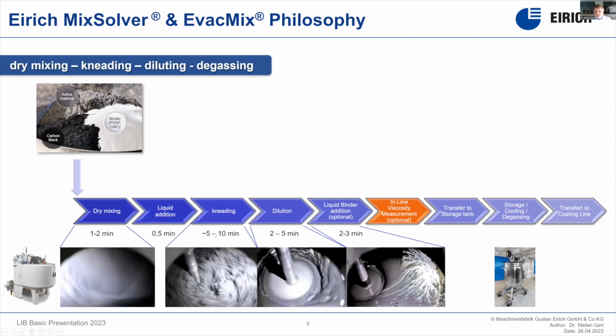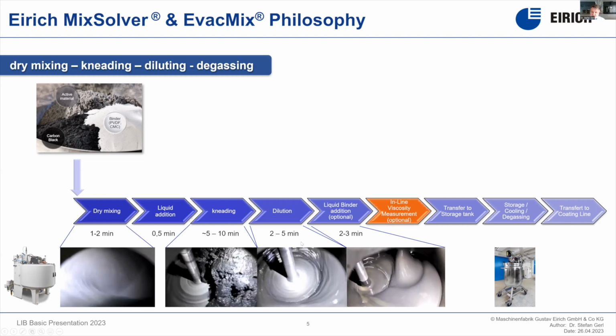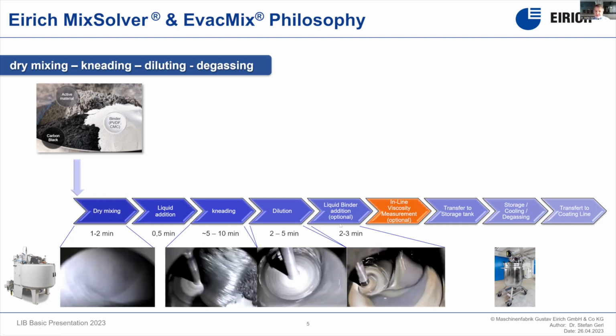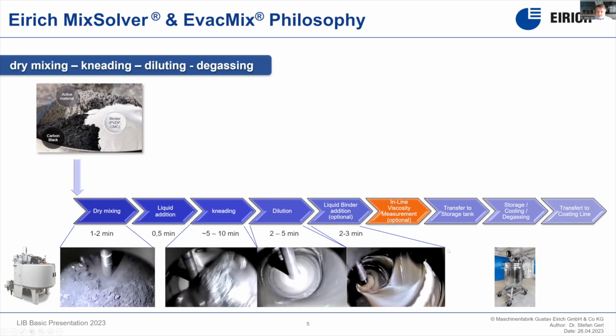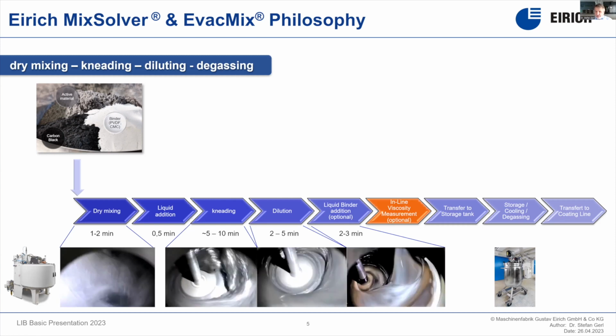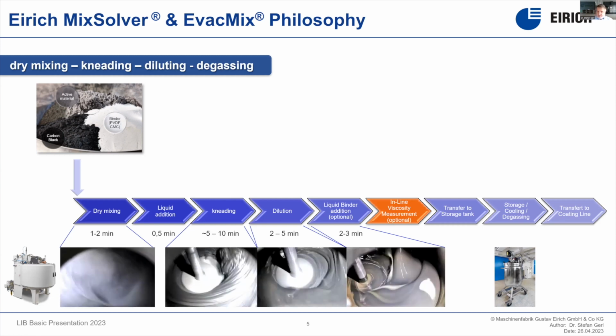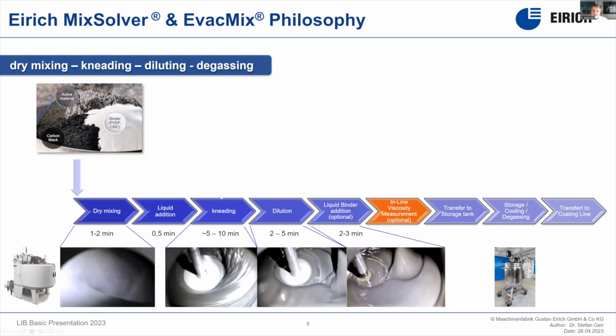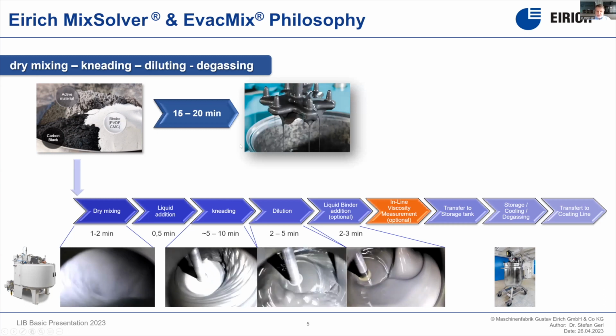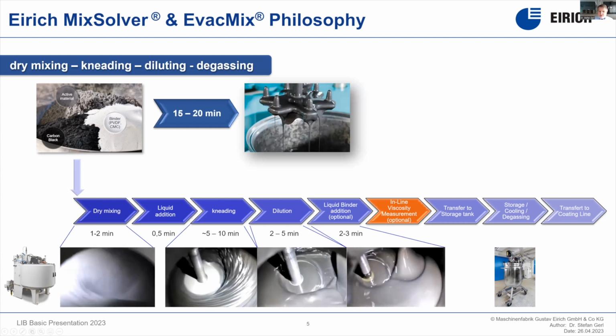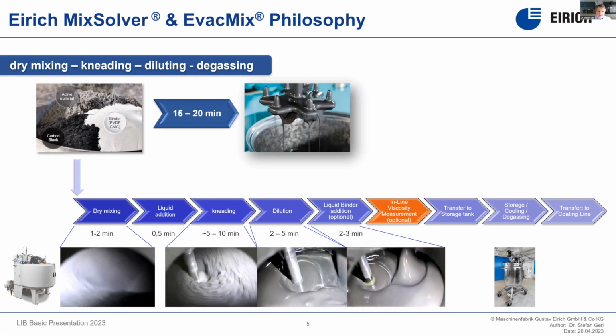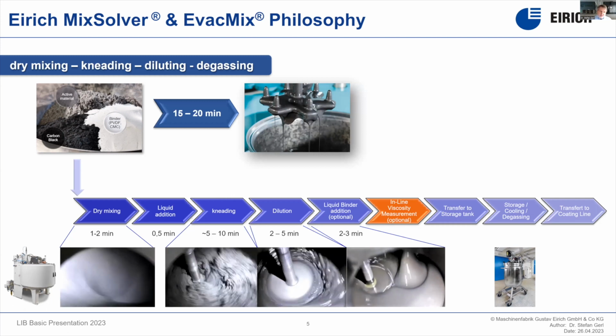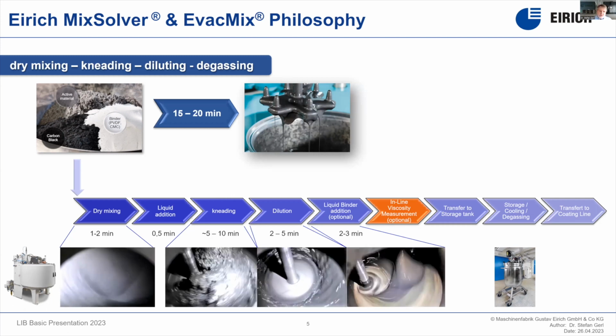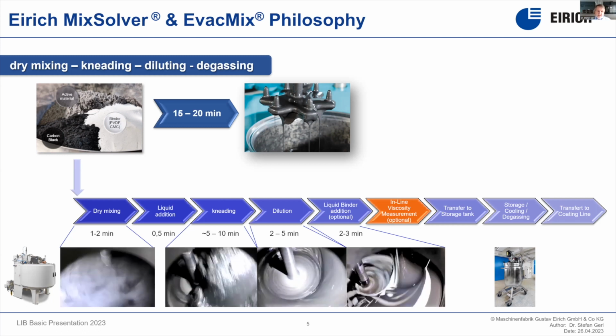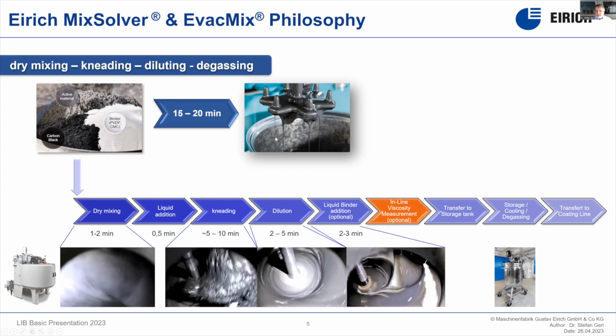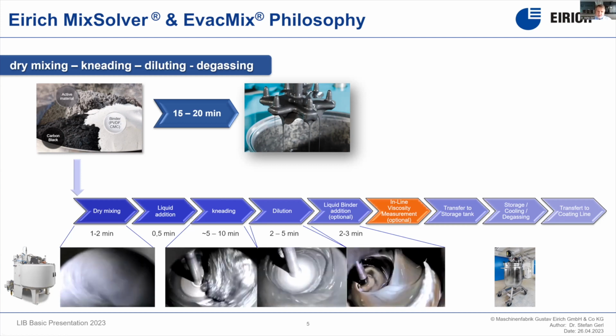So after this most important kneading step, we are then just adding the missing liquid, which typically takes 2 to 5 minutes. When we are going for a complete water-based system, like for anode, where you have a liquid binder like SBR, we are adding the liquid binder, like, let's say, cream into coffee, at low shear rate, so that the overall processing time typically takes 15 to 20 minutes, and this is almost the same for anode or cathode. Anode is maybe a little bit longer because of the SBR addition. The overall batch time, this means from in to out, we are calculating between 30 and 40 minutes, depending on the filling of the machine, because the extraction takes a little bit more time than in the past with our concentric discharge systems.